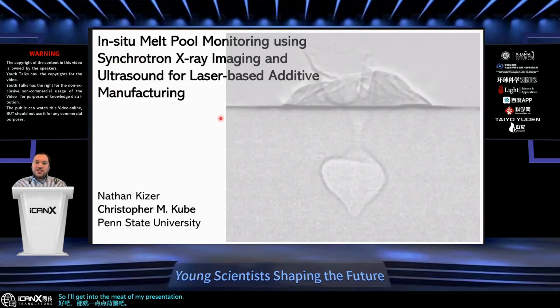So I'll get into the meat of my talk here. I mentioned melt pools. Melt pools are at the heart of this. A melt pool is the liquid region that forms due to the laser interacting with the material and melting it locally. This is actually a cross-section image of the melt pool, or one flavor of a melt pool. This is taken from an X-ray image at a synchrotron source, and I'll be talking about this more later. This is a high enough energy X-ray where you can actually see the melt pool and the weld. There's a liquid region that is contained within this part, and then this area in here is actually vapor or gas. The laser that is creating the melt pool has enough energy where it actually boils the metal and it can create gas inside of the melt pool.